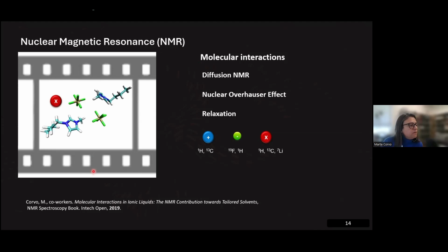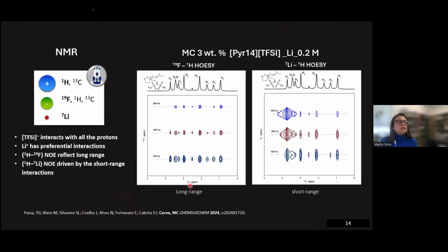So this was to integrate what I'm going to show you next relating to our gel polymer electrolytes. These are gel polymer electrolytes prepared in this work with methylcellulose, and this is the work done in the PhD of Tiago Paiva, already finished. Here we looked at our samples, our gel polymer electrolytes, through proton and carbon towards the cations, and fluorine, proton, and carbon also for the anions. And of course, because our samples had lithium salts in them, we looked at lithium NMR also.